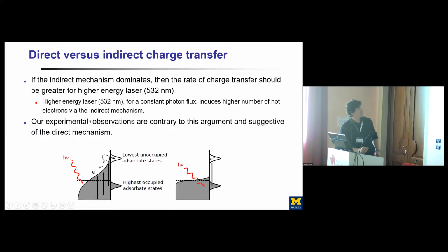So if this indirect mechanism was dominant, the rate of charge transfer should be greater for the high energy laser, because simply we are putting more energy in the system. We would create higher energy electrons, and you would expect that that electron distribution would be hotter, and therefore we would have more electrons that are scattering through this anti-bonding orbital and heating the molecule. And that's not actually what we see. We see that this lower energy laser, 785, actually induces this kind of heating of the molecule.